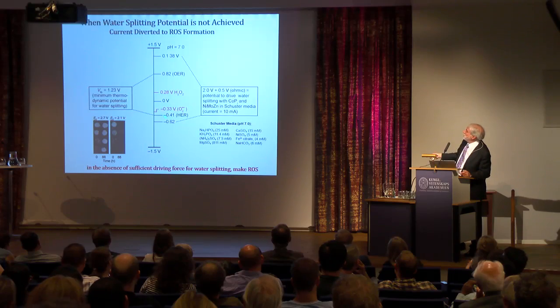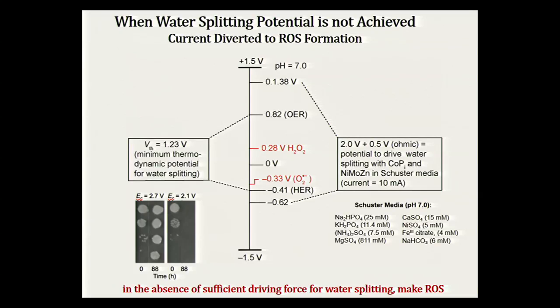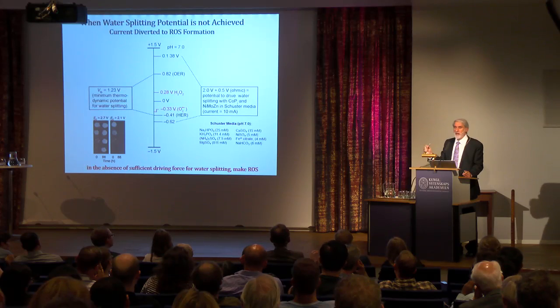If you don't have enough voltage to overdrive water splitting, what happens is, at a potential before you make hydrogen, you can reduce oxygen from the atmosphere and make superoxide. And that makes what's called reactive oxygen species. That superoxide can go to peroxide and attack the DNA of the bacterium and kill it.